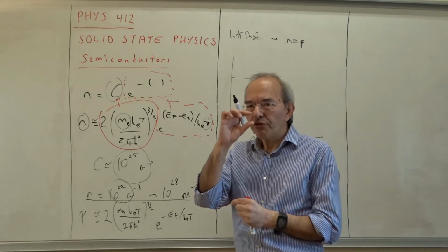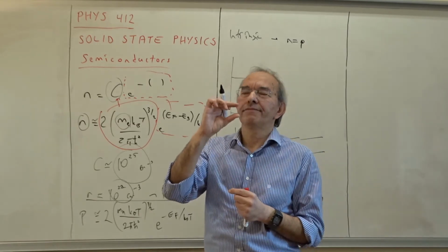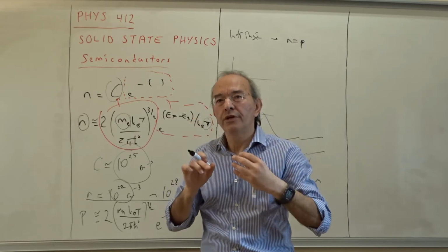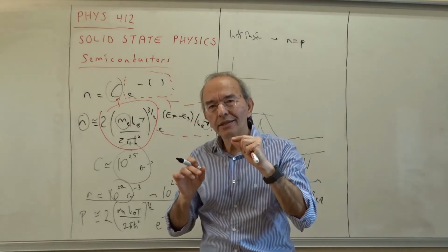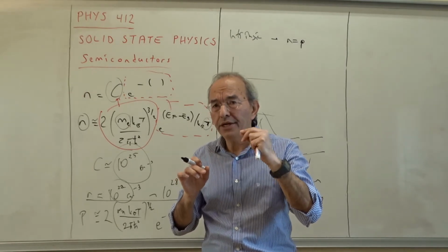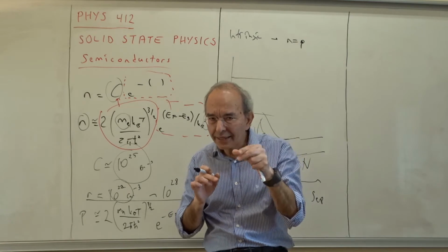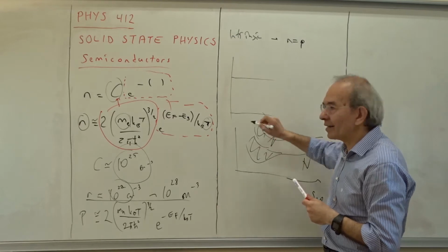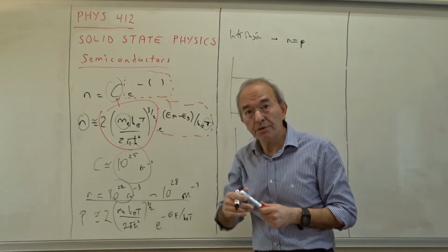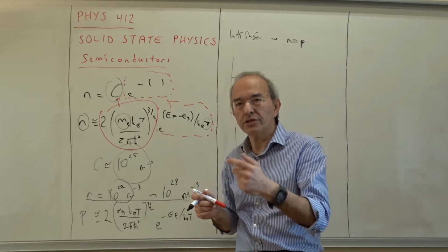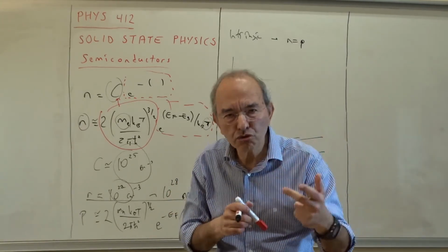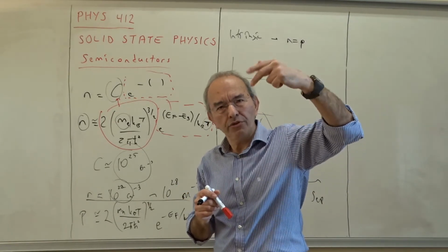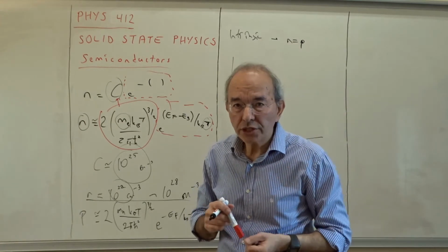So a very small, in general, finite amount of energy interval is divided into an almost infinite number of pieces, so that the distance between two successive energy levels is very, very small, delta E. So these are called bands, and there are gaps between the bands. This is, remember, the band theory of solids in general, whether it's a metal or a semiconductor or an insulator, they all have bands, 1s, 2s, 2p, 3s, etc. Remember those electronic configurations of the atoms.